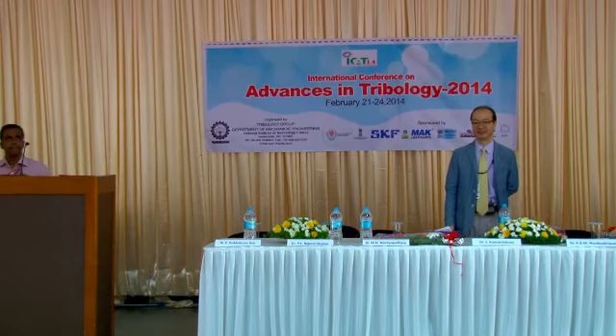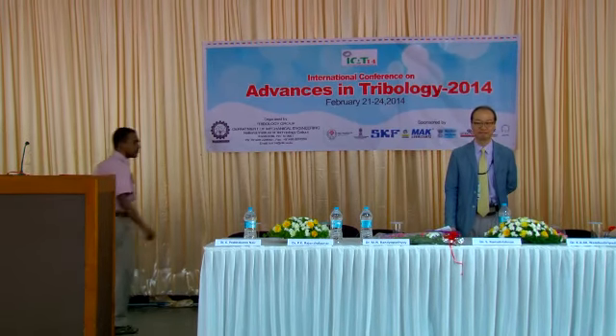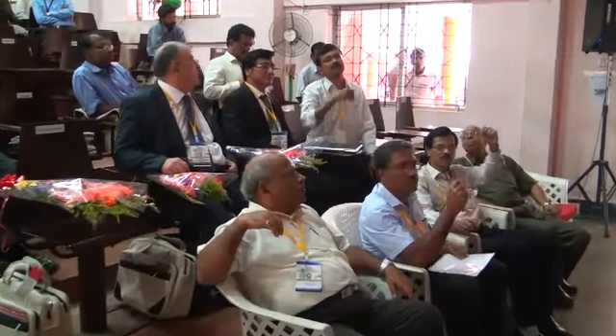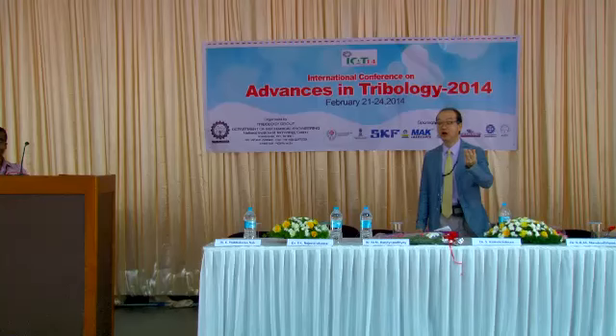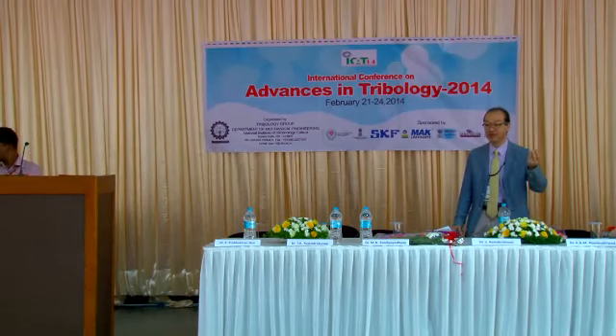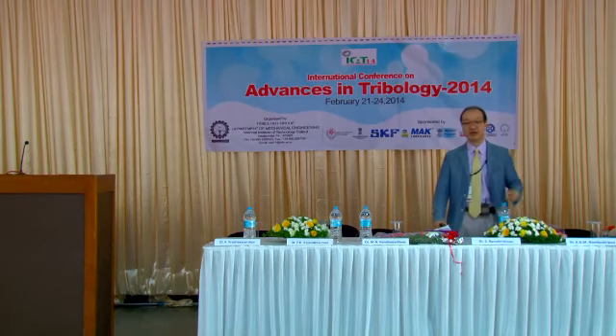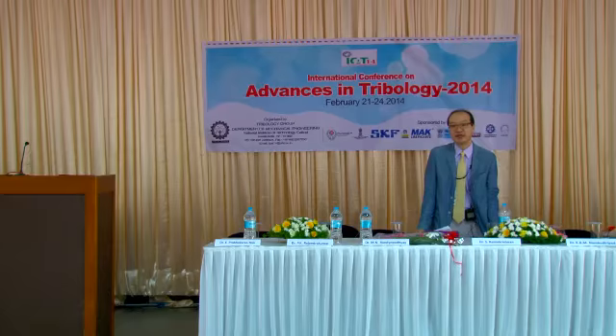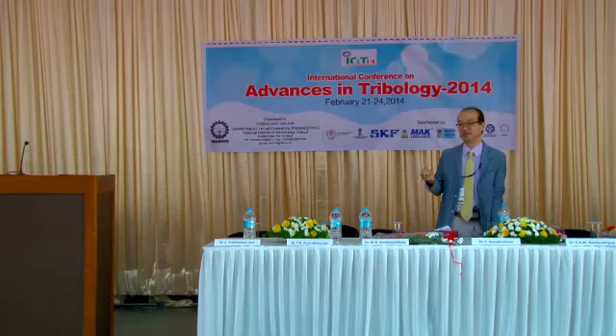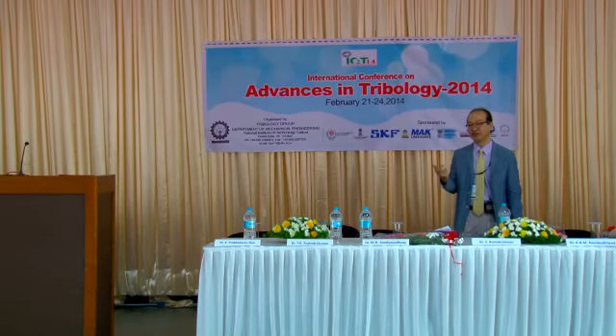Yeah, there have been some experiments where AFM tips are being slid, and they have observed less than one atom being removed per kilometer of sliding. What is your view on that? You have done similar experiments. Okay, the question is, there have been experiments where you have an AFM tip and you do a lot of sliding, and you have one atom being removed from the AFM tip per kilometer. Now, that is questionable. And the problem with this tribological research, especially nanotribology, is that it should be repeatable in another lab. And I'm wondering if anybody else has reproduced that factor.